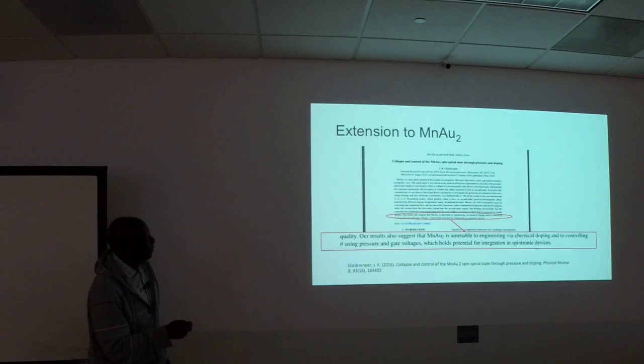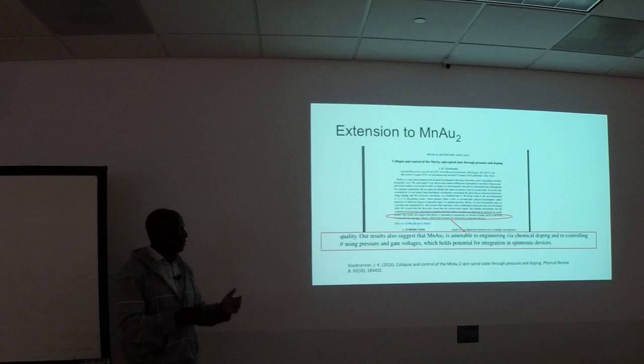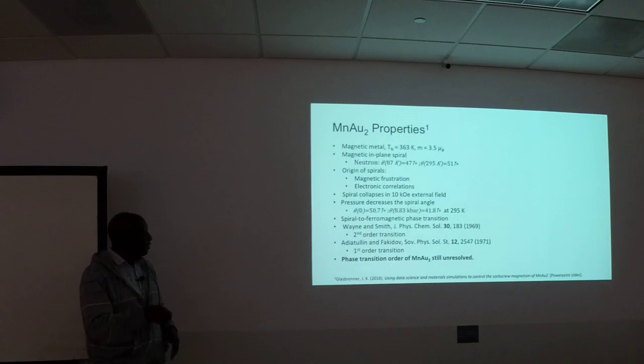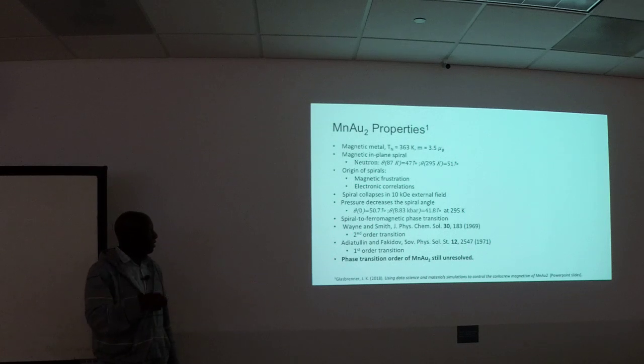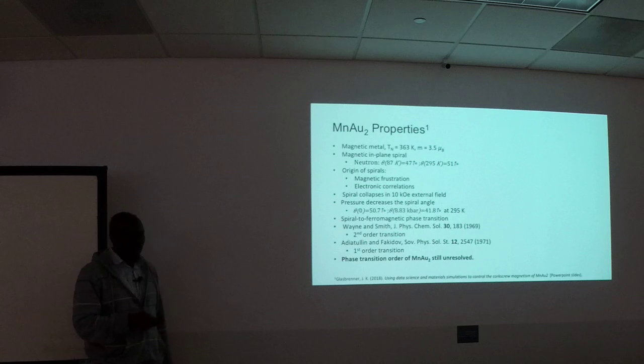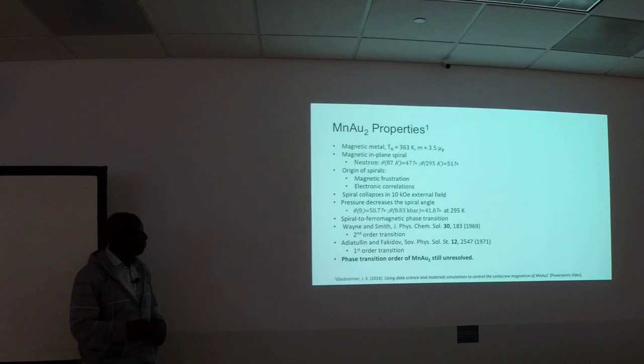This paper by Dr. Glassbrenner, whom I worked with on this, considers, like I said, once you get to greater than two-dimensional cases with the Heisenberg model, it becomes almost impossible to calculate. But in this paper, they did a one-dimensional case with four nearest neighbors to see what the properties are. And so they did these different calculations. What is pertinent here is that different people have observed different transitions and different conditions for the same material. So its phase transition, is it first order, is it second order, is it in between, is still not resolved. And if we can model that, make that definite,